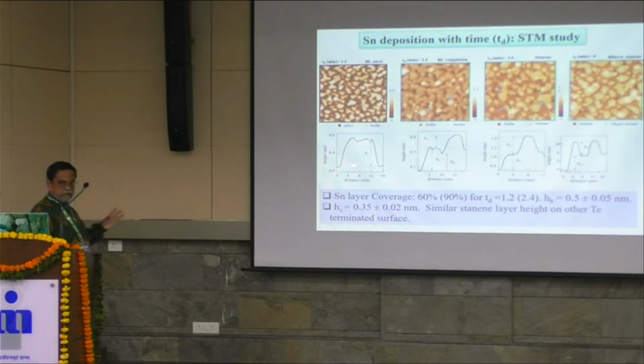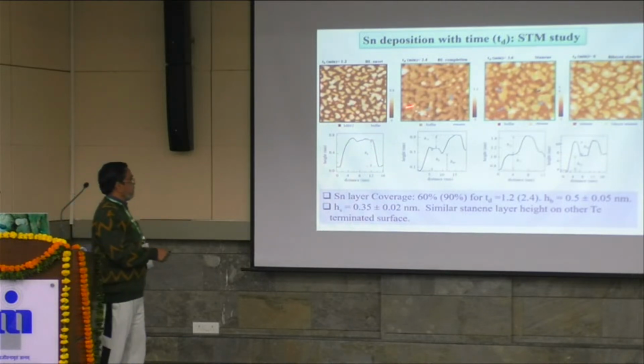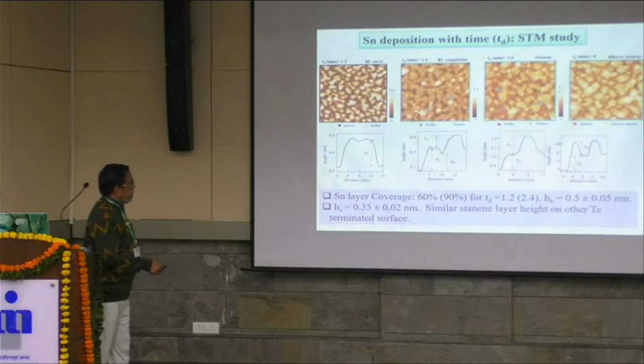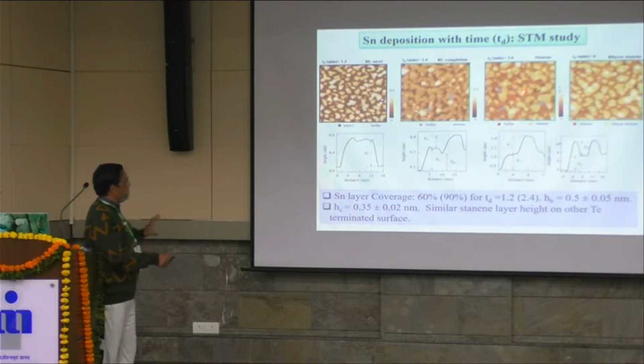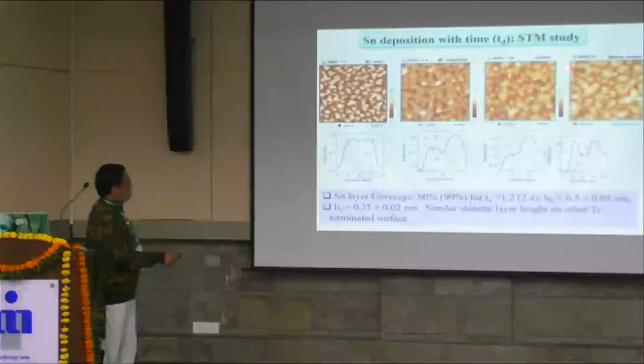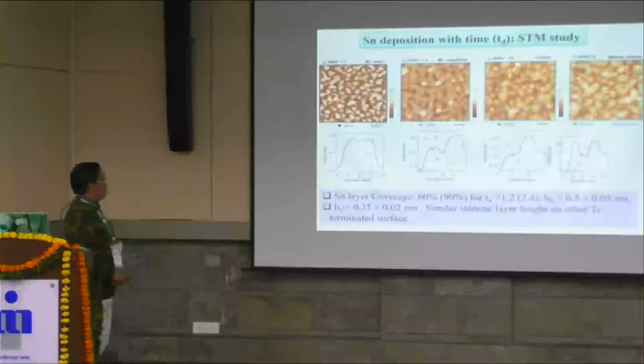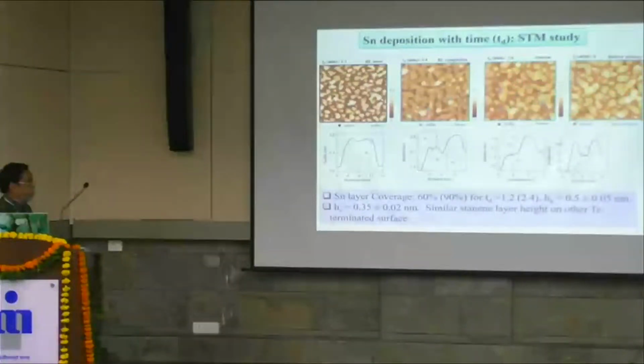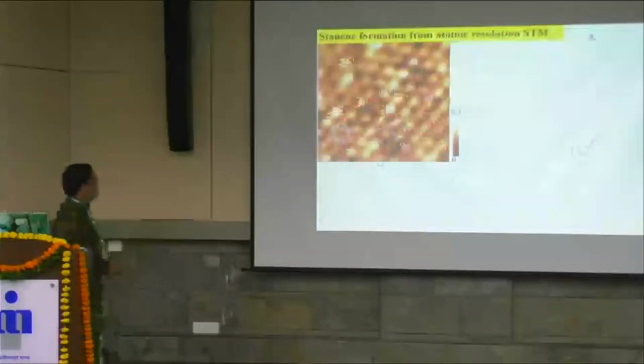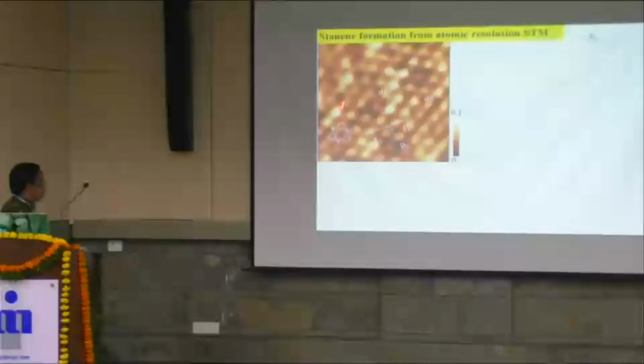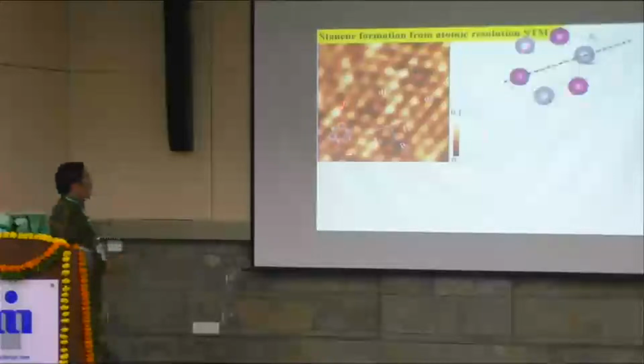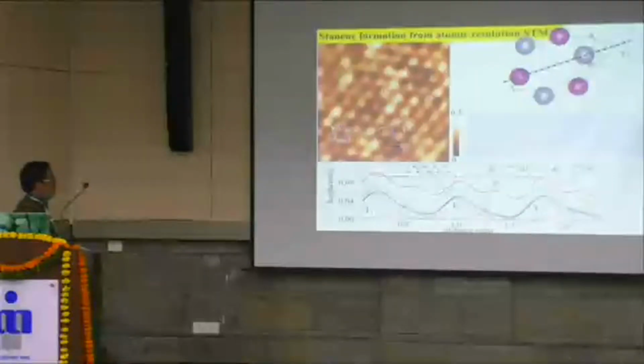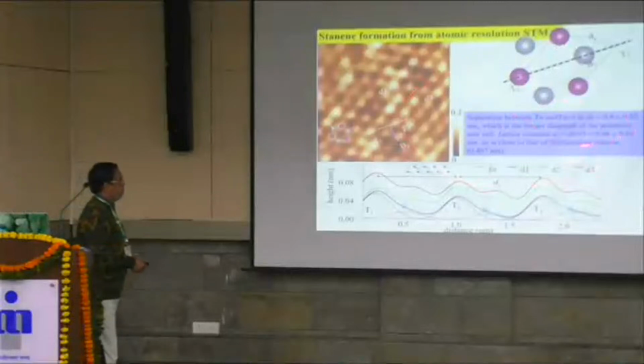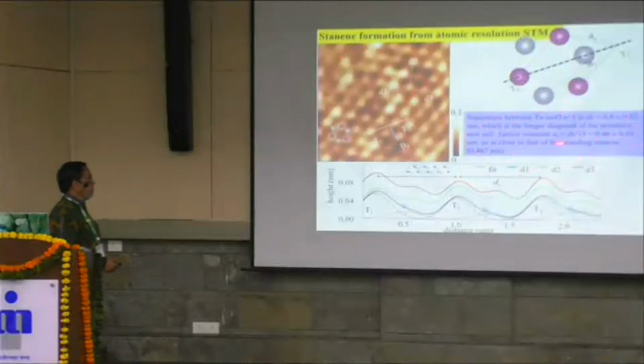It says that this is not a tin layer, this is something else, but ultimately we get the heights to be similar to what we expect for a single tin layer, and we get stanene and bilayer stanene. So now this is again seeing is believing, that we did a detailed analysis of the atomic image. This is the unit cell of tin, and the detailed analysis showed us that yes, indeed, we found out the lattice constants and everything, in agreement with free-standing.